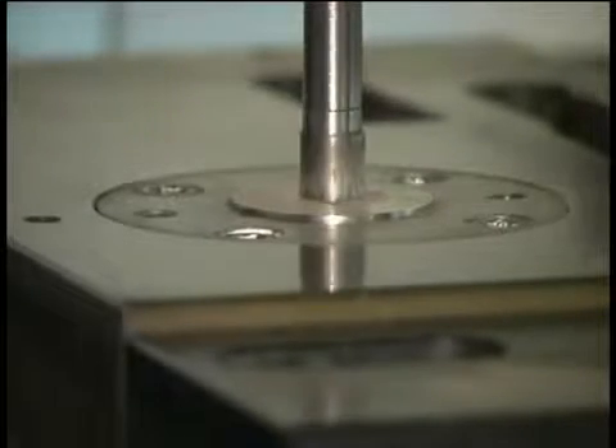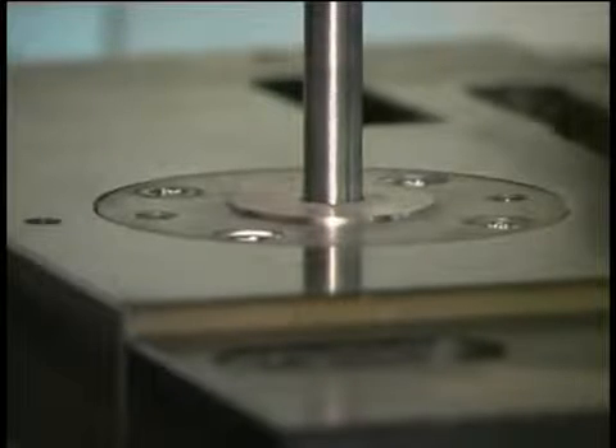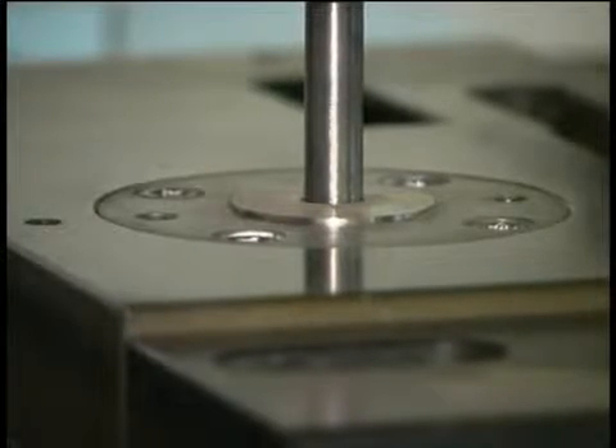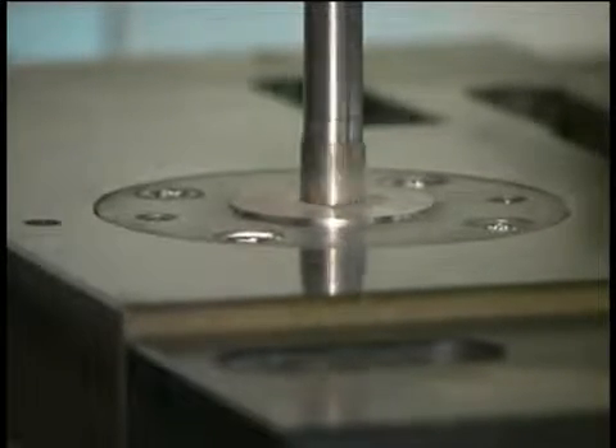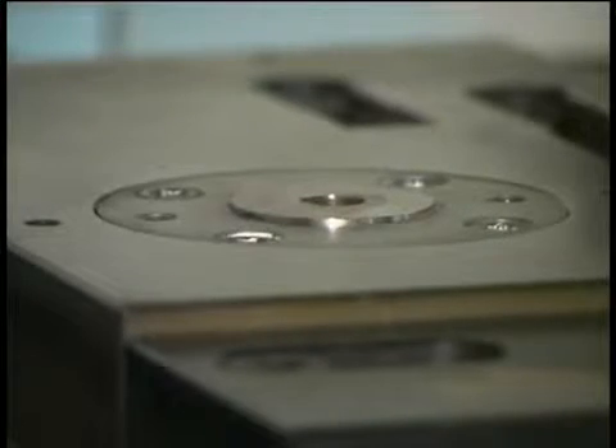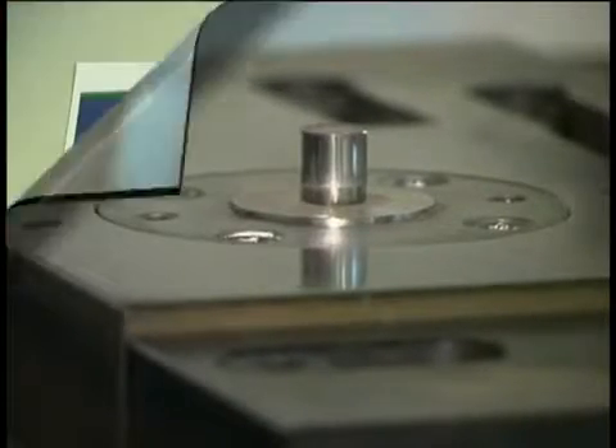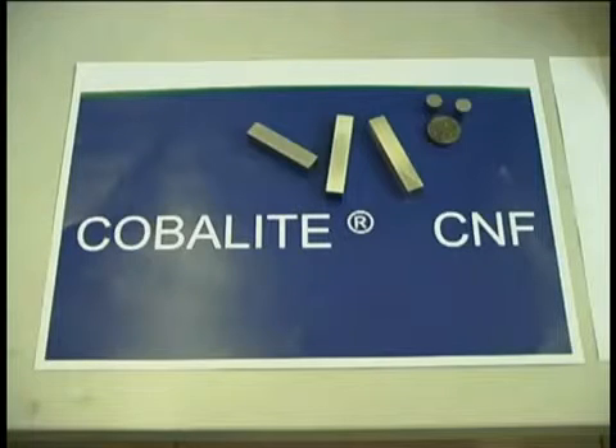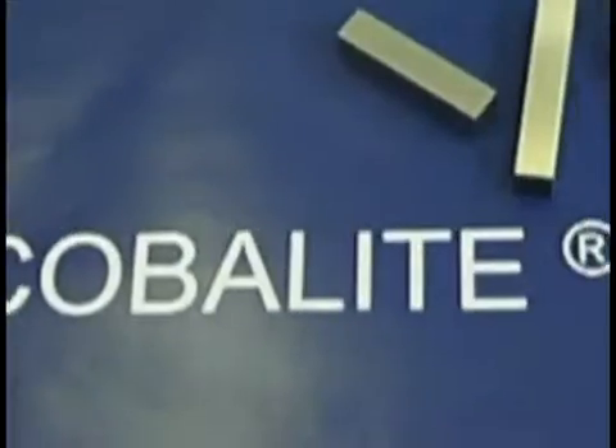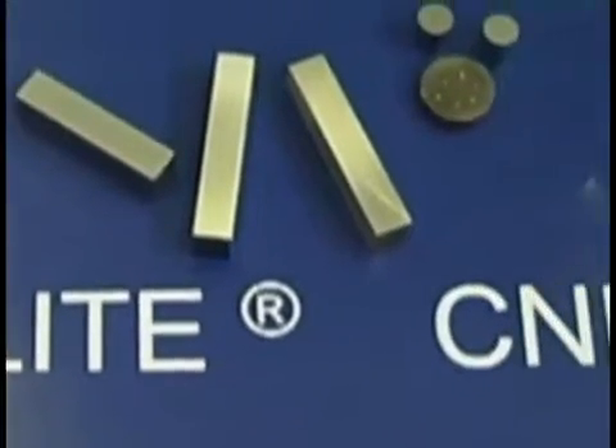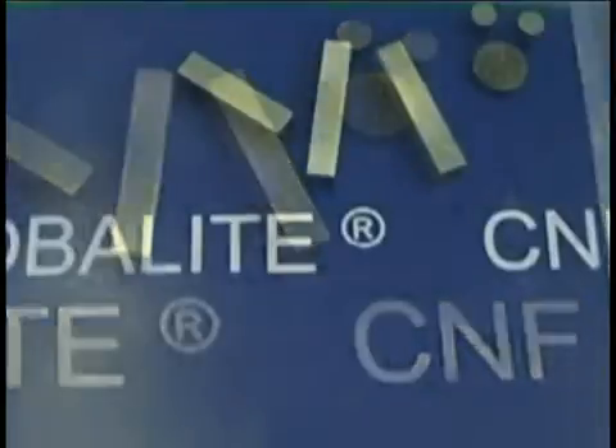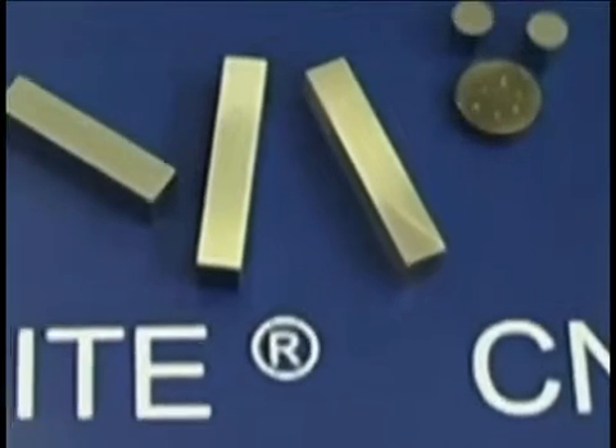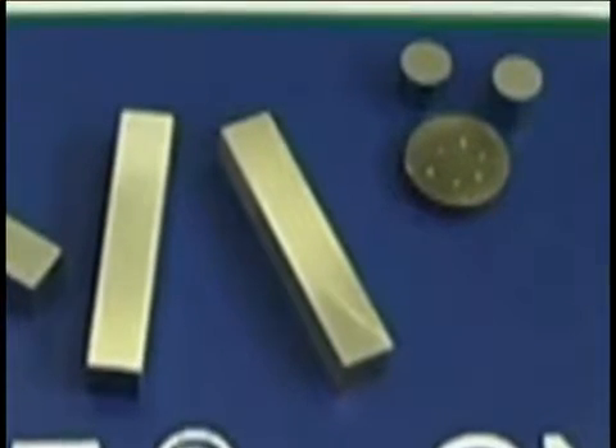In existing pre-alloyed powders, a copper phase and a solid solution hardened cobalt iron phase are used. By way of contrast, in Cobalite CNF, tungsten is used instead of cobalt to provide solid solution hardening in the iron phase. Additionally, tin is used as a solid solution strengthener of the copper phase in order to increase its hardness. Finally, yttrium oxide is used to provide oxide dispersion strengthening to the entire matrix.